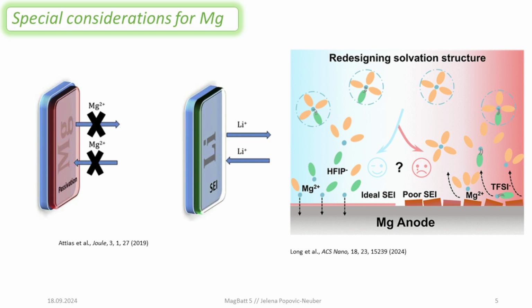And then there is another problem, and that is that in the case of our ideal SEIs, we always imagine it to be a dense, very thin layer because the resistance should be relatively low. But in the case of magnesium anode, we have heard a lot of different kinds of things happen on those interfaces. Either we start with this kind of passivation, where we chip parts off it, so dissolution. There are quite many papers talking about dissolution of the SEI, but there are also quite many papers, in particular the old Aurbach papers, telling us a lot about adsorption. So the processes are even more complex. We have some very complex species in our liquid electrolyte, and these get adsorbed on the surface of magnesium. So the situation seems to be way more complex than in the case of lithium metal.